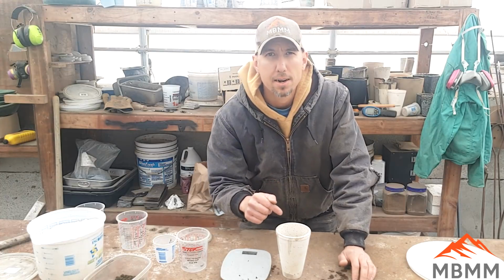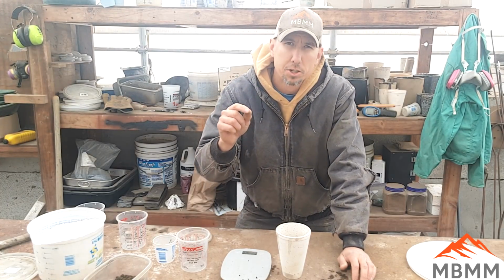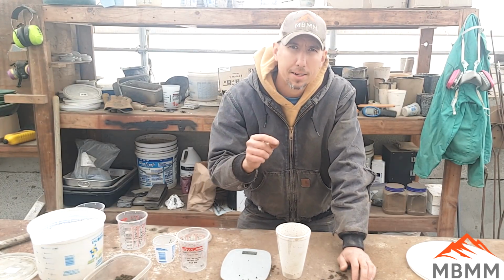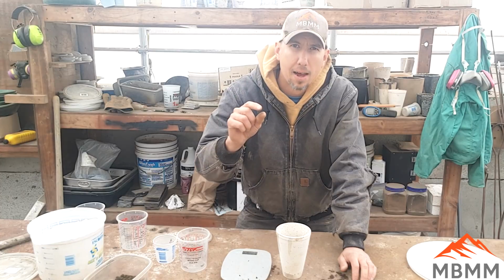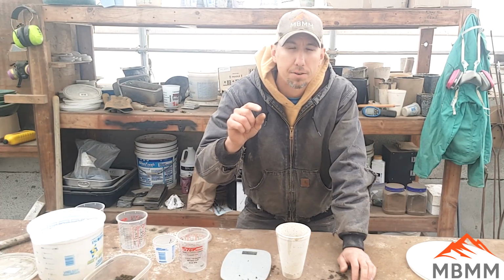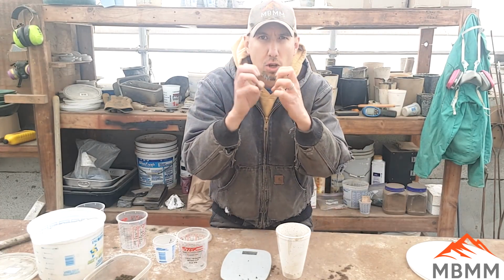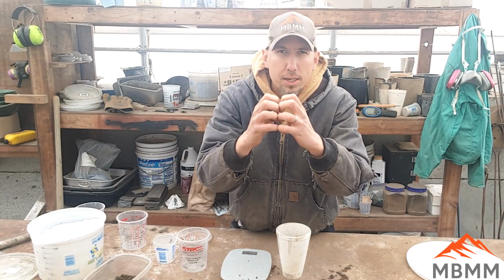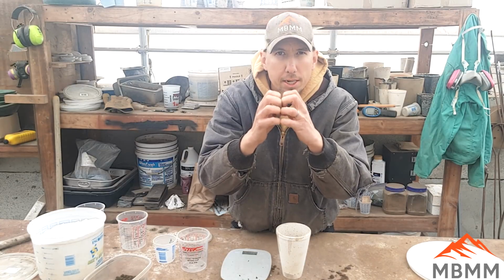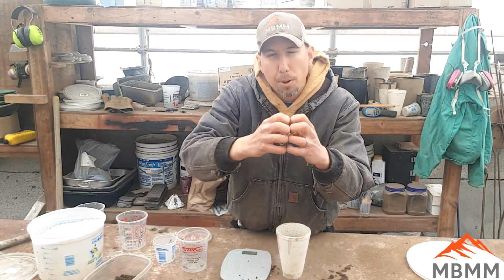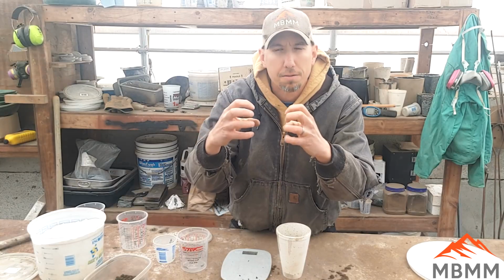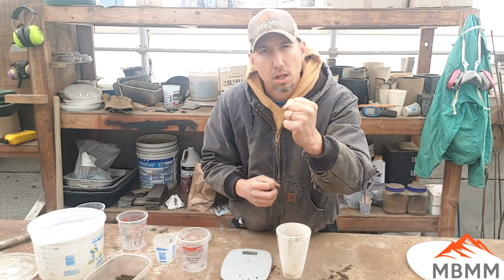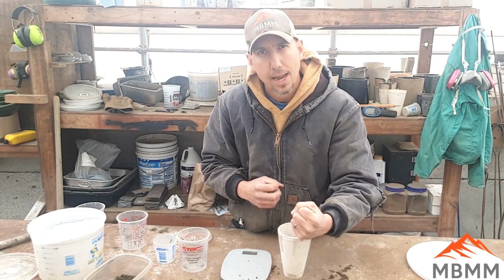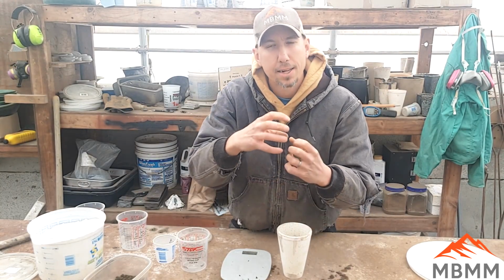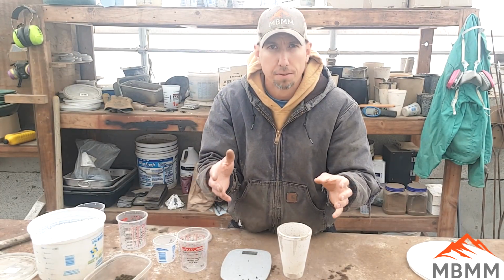And what those iron nails do is the sulfur is very much attracted to the iron. And so if you have a molecule of galena, let's say, a lead and a sulfur atom, as soon as that galena molecule touches the iron nail, it'll pull the sulfur off of that molecule and reduce it to lead metal, which is going to sink down to the bottom of our crucible. And it's going to form iron sulfide, FeS, iron sulfide.